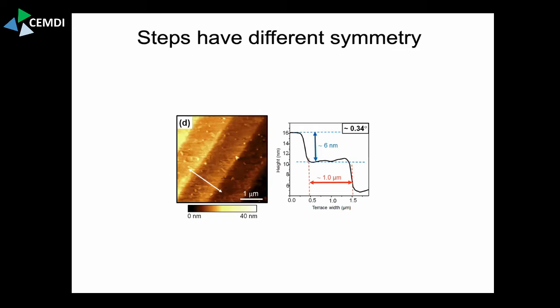As long as you stay on a perfectly flat surface, all the surface atoms have symmetry in plane. They just have a slightly different symmetry with respect to the top. So they can probably stick out a little bit further and get some sort of unidirectional expansion. When you come to the edge, the unit cell sitting at the edge has no boundary at all here. It's not sticking anywhere here. So it can actually relax.